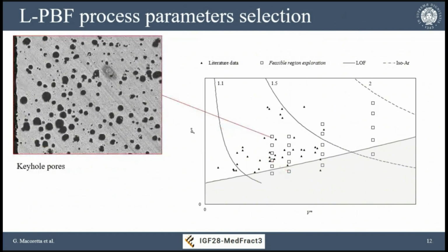When we are far above our region, at higher power but relatively low velocities, we have the occurrence of keyhole, as you can see from this huge number of white round pores that are typical of keyhole in the L-PBF process.